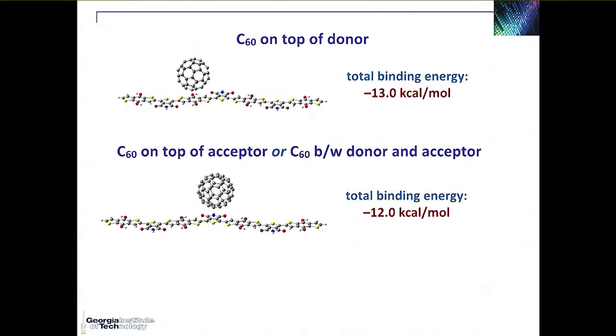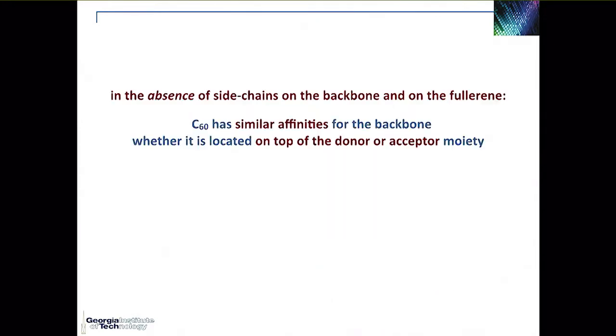If the fullerene goes on top of the acceptor or in between the donor and the acceptor, the binding energy is basically the same. The binding energy becomes very different when the C60 comes on the edge of the oligomer chain, in which case you have a binding energy that's nearly half of the one you had when the fullerene sits on top of the backbone. And of course, with the fullerene sitting on top of the backbone, what you maximize is the dispersion, the induced dipole interactions among the pi electrons of the backbone and the C60.